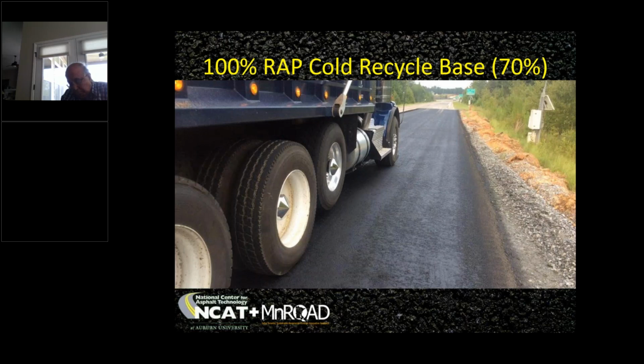And regarding reducing the structural contribution of specific materials, this is a picture from a 100% RAP cold recycle base layer that we put on the track in 2015. This section is being directly compared to another section that has a conventional hot mix asphalt base, and what we're finding is that the structural contribution of this layer is about 70% of the hot mix equivalent of this layer.